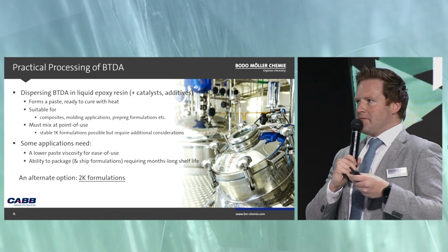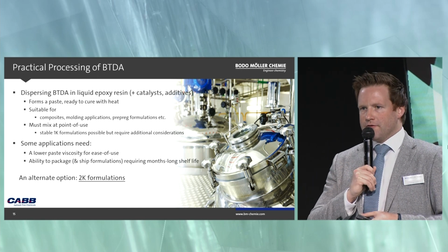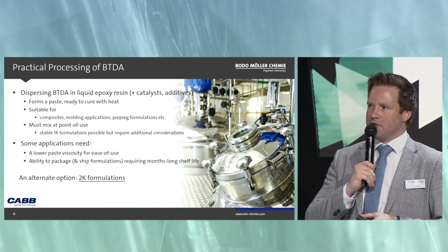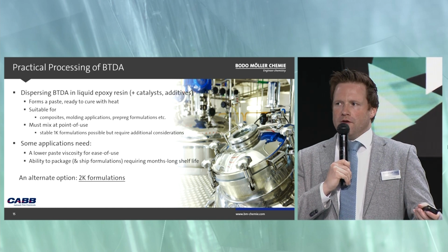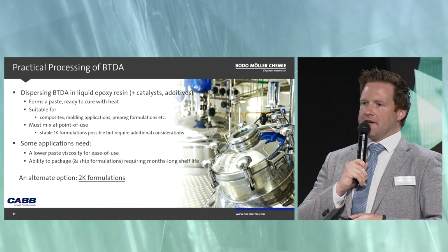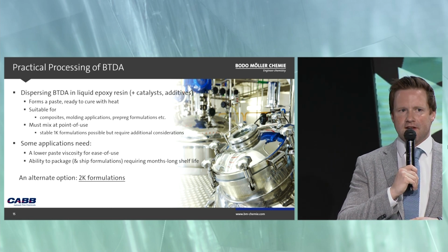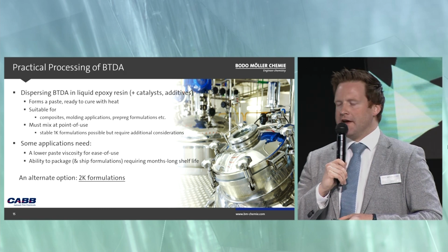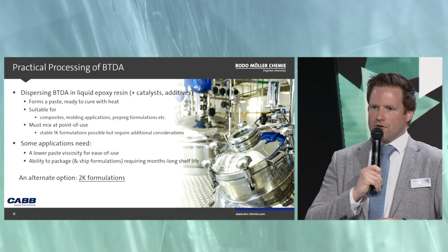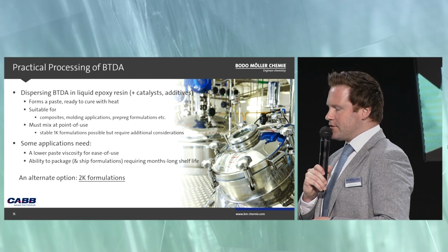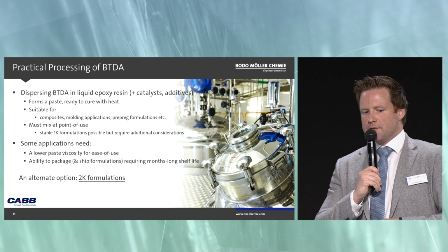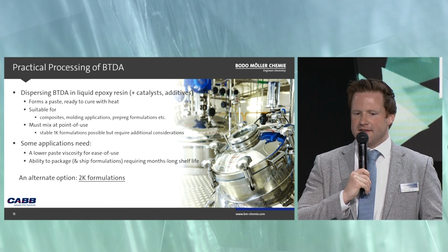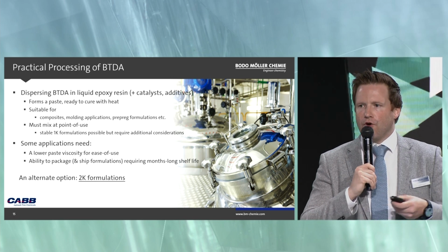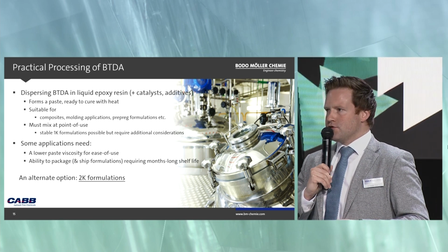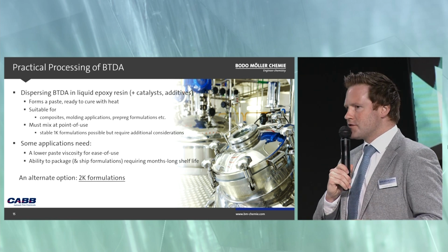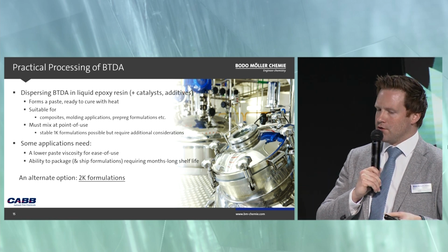Of course, there are also some topics to keep in mind when formulating such BTDA-based epoxy systems. One possibility, for example, is to disperse the curing agent in the liquid epoxy resin. Like I mentioned before, we are talking about a solid material. It is not completely soluble in epoxy resin. So what you need to do is disperse it in the liquid epoxy resin. You can use, for example, different catalysts or also additives, and then you form a paste which is ready to use and, for example, can be perfectly used for tow-preg, prepreg applications, also adhesives.